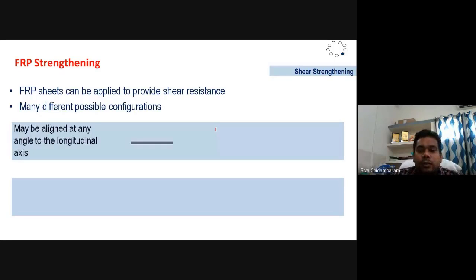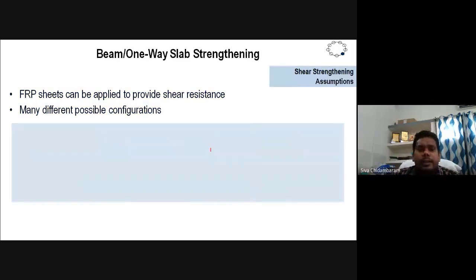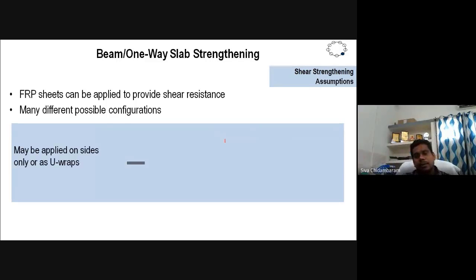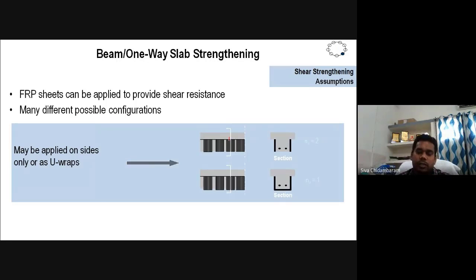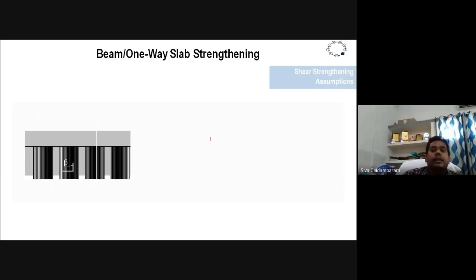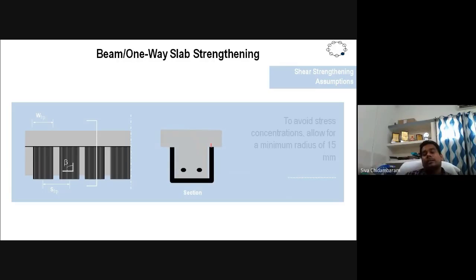So next one is called FRP wrapping. Everybody knows FRP, and everybody may tell me, sir, we know about FRP strengthening. So I won't focus much on this. I will focus only on pre-stressed FRP. FRP is a fiber reinforced polymer. Polymer means the epoxy we are using to strengthen. It is a performance-oriented material because instead of going for RCC jacketing, you can use thin FRP, which will not increase the cross-sectional size of your RCC structural elements, and without increasing the cross section, you can increase the stiffness and strength, but you can't increase the ductility. That's not possible using FRP in beam strengthening.